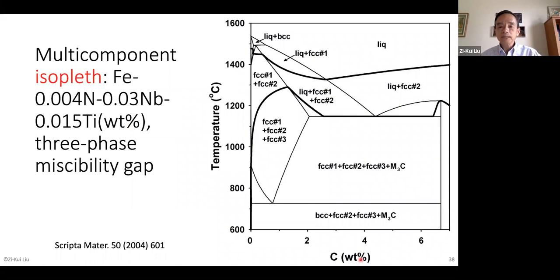This one's interesting, I did this isopleth. It's a multi-component system, and the only way we can visualize them is isopleth. So I fix nitrogen content, fix niobium content, fix titanium content, and the temperature as a function of carbon. So that's a multi-dimensional section with fixed compositions. And then you can see that you have liquid, you have different phases, right? And you can partially apply the phase boundary rule for it.